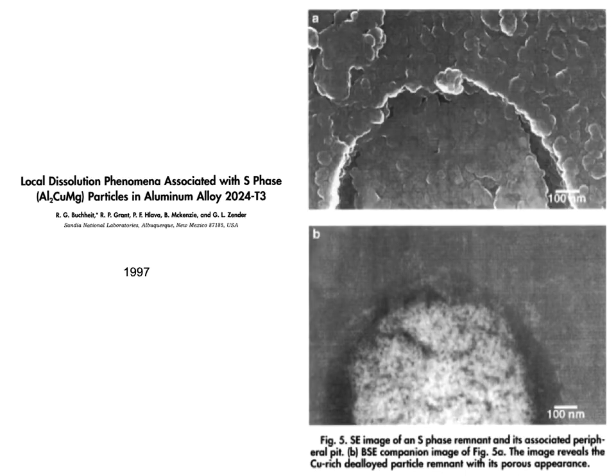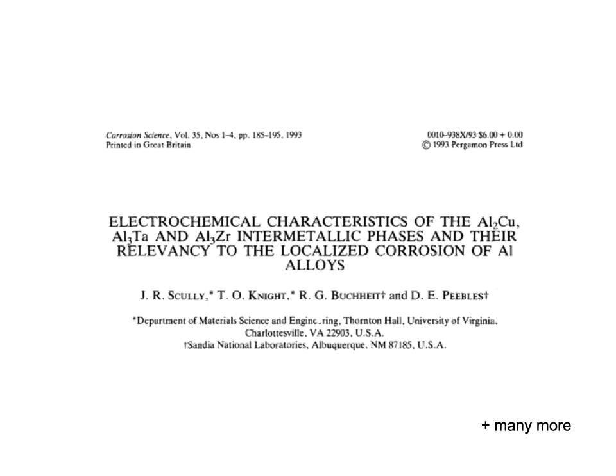Now, shortly after that study, Rudy also revealed an important phenomenon, namely the de-alloying of S-phase in 2000 series aluminium-copper-magnesium alloys. This revelation was actually a direct function of the advent of a step change in scanning electron microscopy and the resolution that came from field emission gun electron sources. What we see here in these images is copper redistribution and incongruent dissolution of a microstructural feature, which is S-phase.